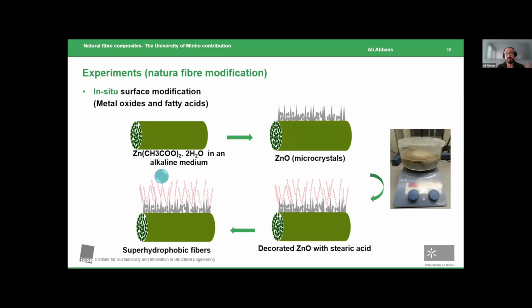So in order to improve the hydrophobicity of the natural fiber, we would decorate this microstructure with a fatty acid called stearic acid. So stearic acid is a superhydrophobic molecule. I'm sorry, I'm going to bore you with a little chemistry today, but it's essential to the core of the work that has been done. So it's a superhydrophobic molecule. It can repel water, and it's technically a wax. So you decorate it through the stearate, zinc stearate molecule, and you would end up with these superhydrophobic fibers.